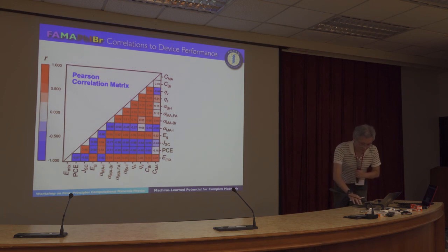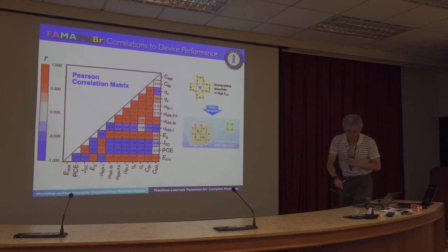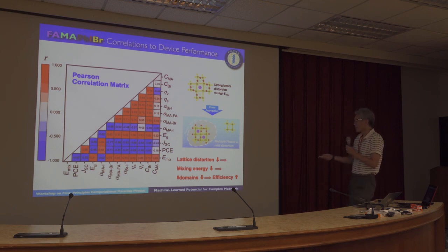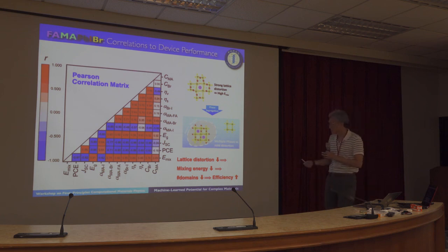And finally, we can reach the conclusion about lattice distortion. When we have a strong lattice distortion, this leads to high mixing energy, and this is going to trigger phase segregation. So it's going to segregate into phases that are not so distorted. As a result, you have a domain boundary, and this basically creates a lot of defects. So this is not good for carrier transport, and therefore leads to a decrease in the efficiency.